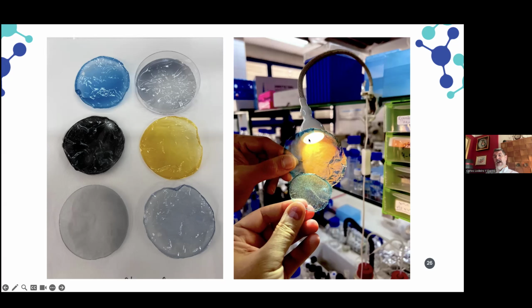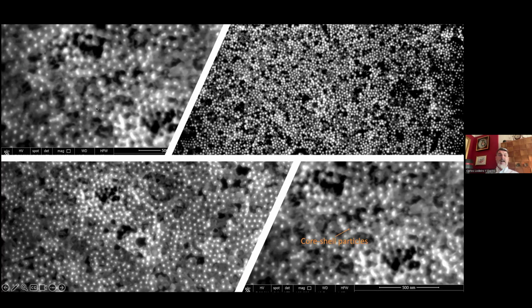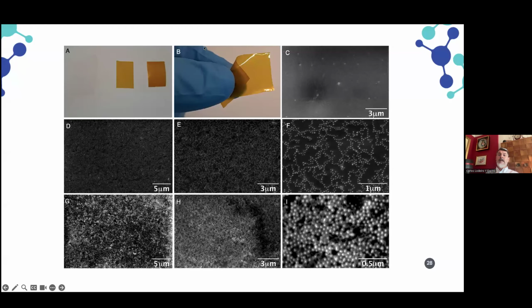If you look through a light, you can see there are spots in which you can concentrate the nanoparticles. Then, looking at the scanning electron microscopy, you see a huge number of nanoparticles concentrated in the network of the polymer. Also, at high resolution you can see the silica core-shell layer maintained inside of this polymer. The most important thing is that even after applying these nanoparticles in a huge concentration, you can observe in panel B that the polymer is completely flexible.